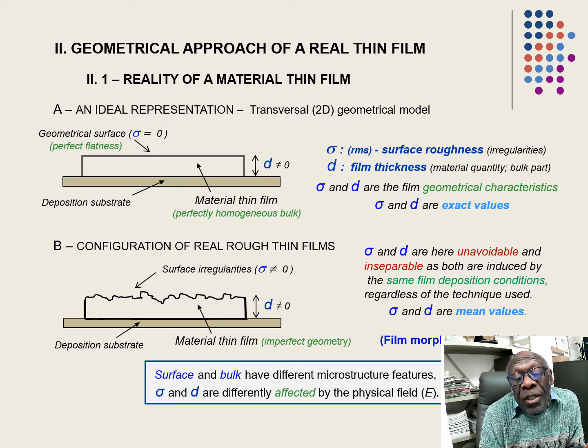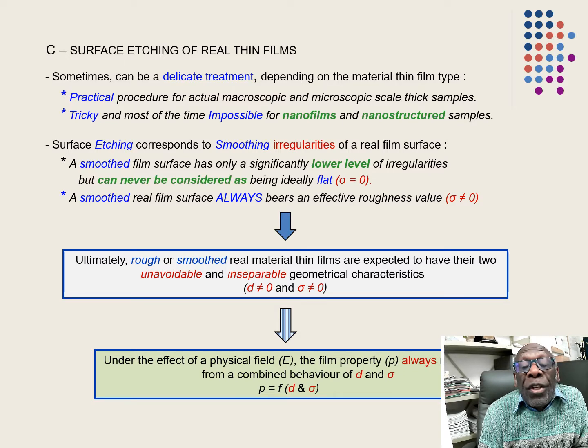And now, generally, when we are dealing with a real material thin film, the trend is of course to make it more perfect, as close as possible to the perfect film. That means we apply an etching treatment. But everybody knows that etching treatment is removal of a part of the material. In that case, the etching treatment is practical only for thick samples. When you are dealing with nanofilms or nanostructured samples, it is very dangerous, sometimes tricky, sometimes even impossible, because you might remove all your material and then you won't continue doing science.